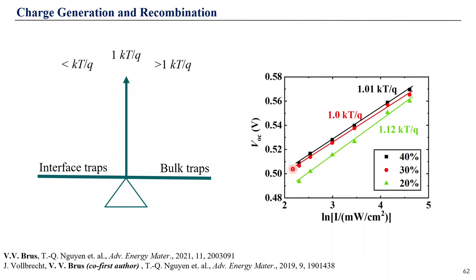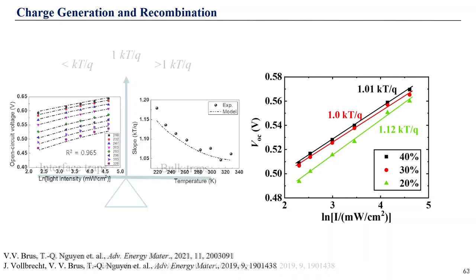So the only option, in the scope of this measurement of VOC versus light intensity, to double check if a slope of 1 kT over q is really evidence of pure bimolecular recombination is to measure temperature-dependent VOC versus light intensity. In that case, if the slope does not change with temperature and remains 1 kT over q, that's good evidence of pure bimolecular recombination, but that's not often done.